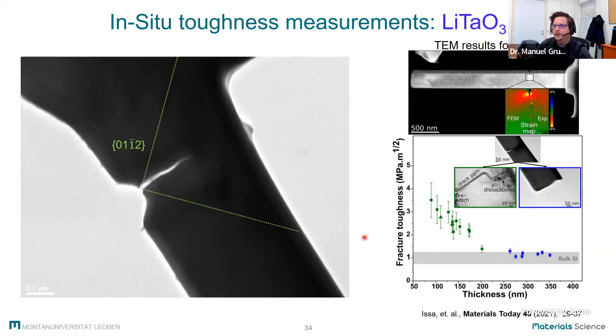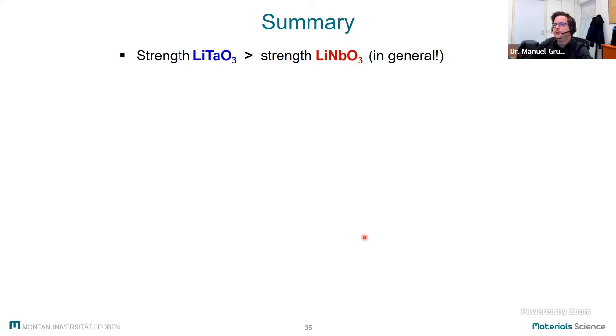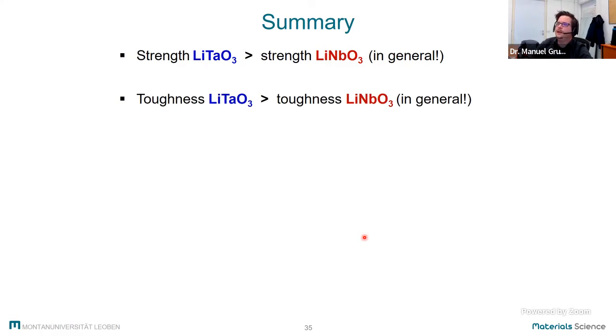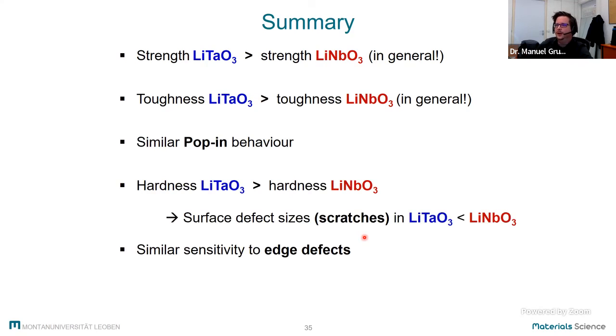So at this point, I would like to come to the summary. I could show you today that the strength of lithium tantalate is higher than the strength of single crystalline lithium niobate. This is due to the higher toughness of lithium tantalate and also due to the higher hardness of lithium tantalate, which lead to less severe surface defects in lithium tantalate compared to lithium niobate.